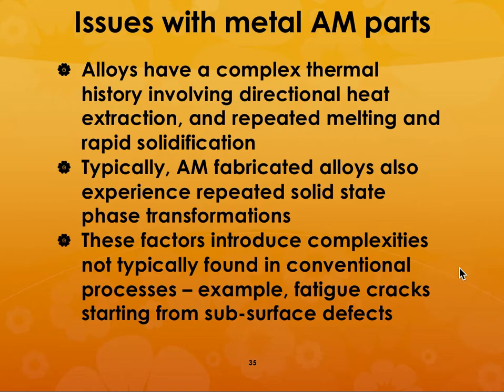So what are some of the issues related to metal additive manufacturing? Most importantly, the alloys have a very complex thermal history, because the microstructure is going to be different in different directions due to the heat extraction and the supplying of the heat, and due to repeated melting and rapid solidification. Because of that, you are also going to have repeated solid state phase transformations, especially if you are close to that temperature range. These factors will introduce complexities not typically found in conventional processes.